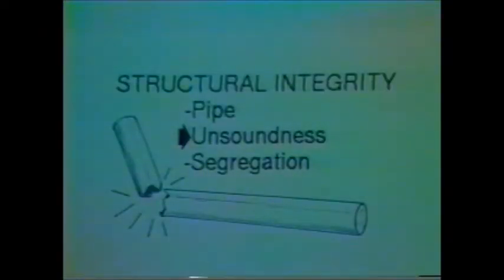Unsoundness is an internal defect that may be caused by too high a casting temperature and too little hot working. Often called porosity or looseness, this defect occurs during solidification of a cast form, when dendrites, very long crystal grains of steel, grow inward from the already cool solid skin. As the steel form cools and contracts, the dendrites tend to contract more than the solid skin, leaving open areas between the grains near the center. Atmospheric oxygen never reaches these surfaces, so adequate hot working can re-weld them into a solid bar again. This defect can sometimes be detected by ultrasonic inspection.